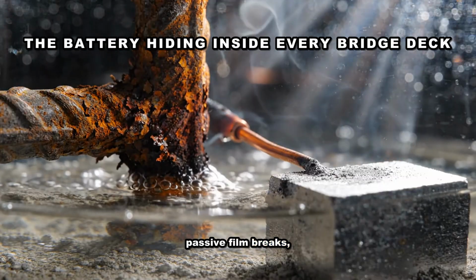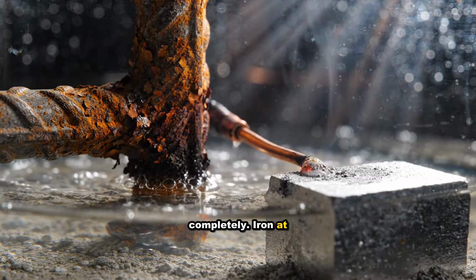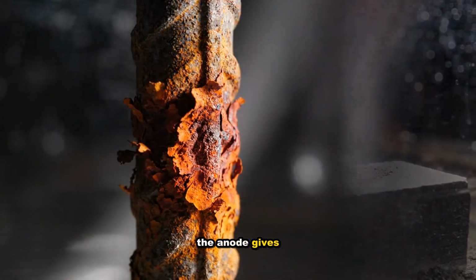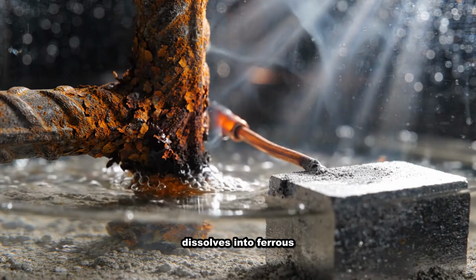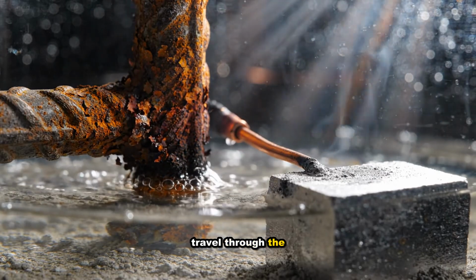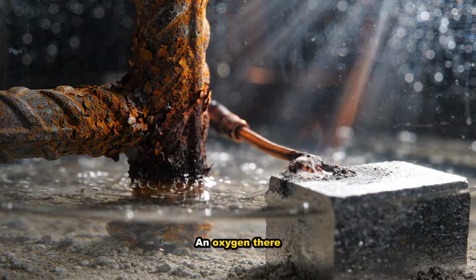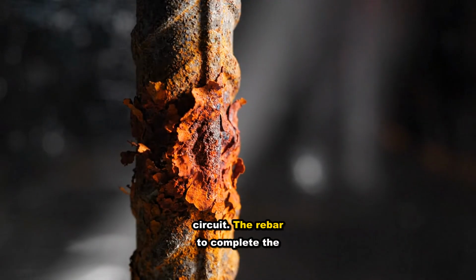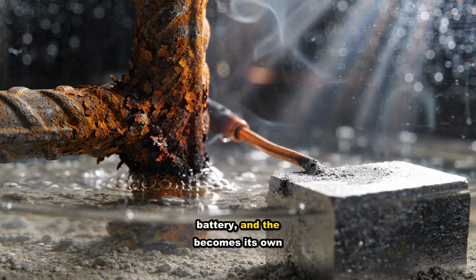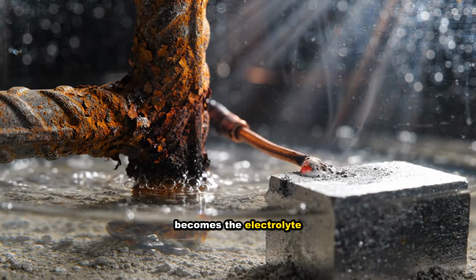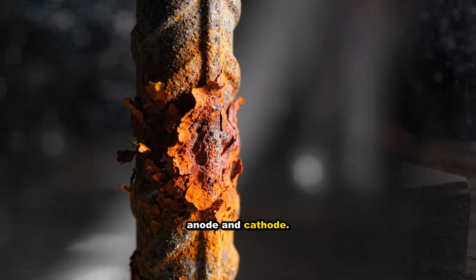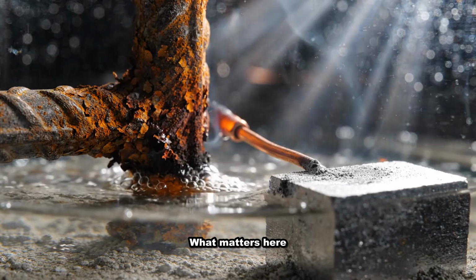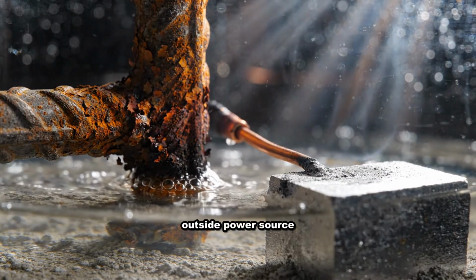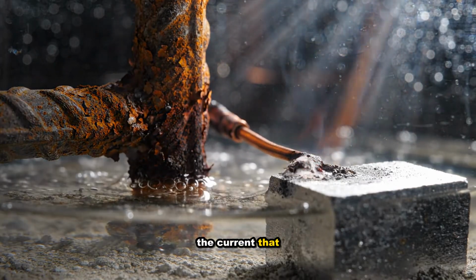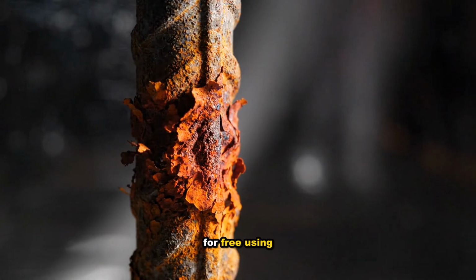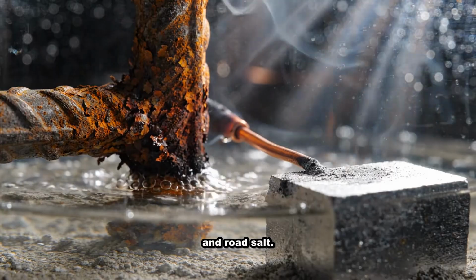Once the passive film breaks, electrochemistry takes over completely. Iron at the anode gives up electrons and dissolves into ferrous ions. Those electrons travel through the steel bar to a cathode site, and oxygen there combines with water to complete the circuit. The rebar becomes its own battery, and the concrete pore water becomes the electrolyte carrying current between anode and cathode. What matters here is that this reaction needs no outside power source at all. The bridge is generating the current that destroys it continuously, for free, using nothing but rainwater and road salt.